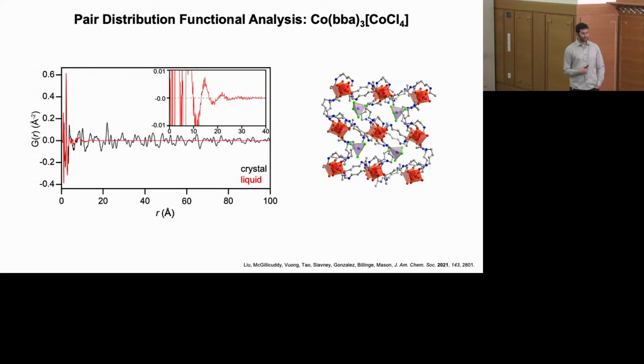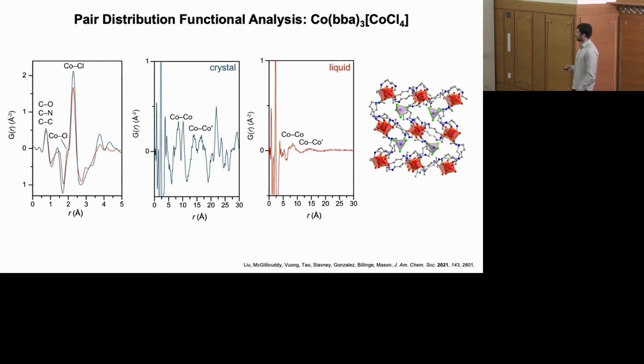So we can also do pair distribution function analysis. This is a total scattering X-ray based technique that gives insight into the local structure of disordered materials to look at the structure of the liquid states of these materials and compare it to the glassy state as well. And one of the interesting things we see here is very similar kinds of structural features at short distances, meaning that the local structure of these materials in the disordered and ordered states are very similar, even though there's no long-range order in the liquid or glass phase. And then we see structural correlations in the liquid at much larger distances, 10 to 30 angstroms, that are indicative of preservation of longer range order that's very similar to that in the original crystalline material. And that's highlighted here.